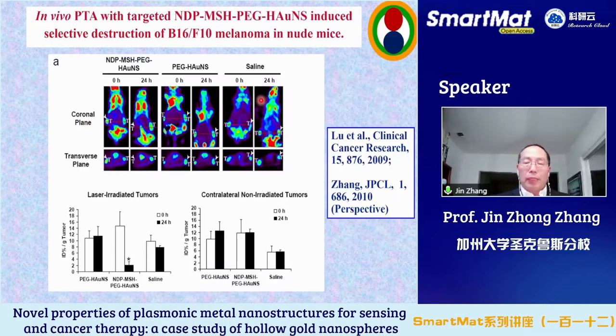And this is an example, okay? So let's focus on this spot right here. This is a cancer spot. So the HGNs are injected through the tail vein of the mice. You inject it, you wait for 4 hours, then you shine light, then you wait for 24 hours. You see this spot here? It's gone. The cancer is removed. The right-hand side, the control, grew doubled in 24 hours. So it's a very aggressive cancer.